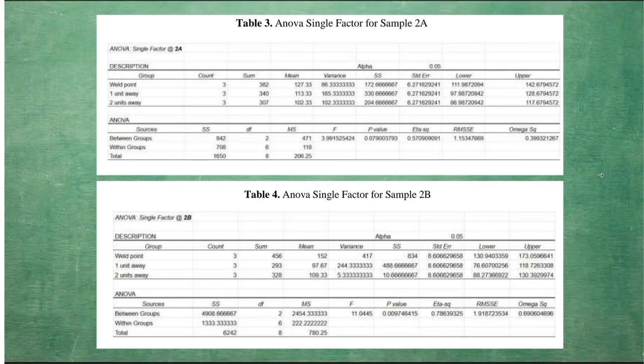For table 3, we have a p-value of 0.0790, which is above the significance level of 0.05. Therefore, we fail to reject the null hypothesis, indicating there is no significant difference in hardness values across the measurement locations. For table 4, we have a p-value of 0.0097, which is below the alpha level of 0.05. We reject the null hypothesis, and we have an omega squared value of 0.691, which indicates a large effect size, confirming that the measurement location influences the hardness of the sample.